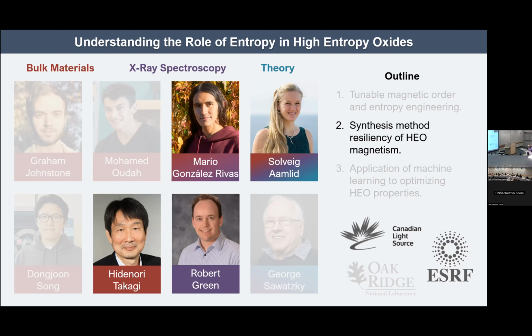But why do you have to be at high temperature? Oh, because you mean if you just wanted to measure the magnetically ordered volume fraction? Okay, so my assumption is that if we have non-magnetically ordered regions, they would be on a kind of nano domain scale, and the muon would still feel the magnetism at that length scale. So I'm not imagining that we have micron length scale non-ordered regions. Yeah, that's my feeling, but it's probably worth doing.